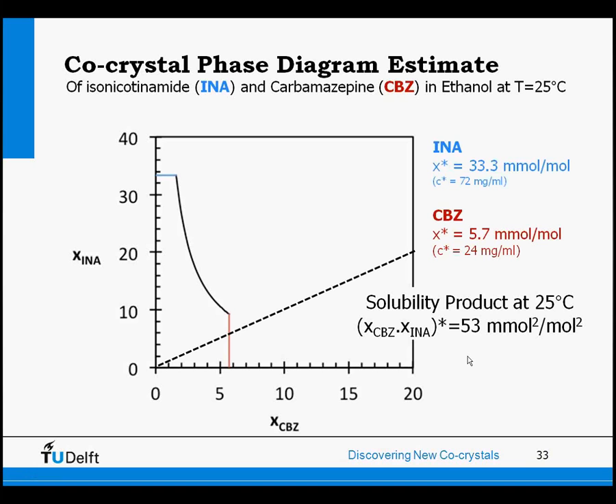And this line is governed by the solubility product of 53. And you see that the stoichiometric line does not really go through the co-crystal region. So if you would crystallize isonicotinamide and carbamazepine from 1 to 1 stoichiometric solutions, you would not obtain co-crystals from those solutions. You need solutions that contain about 6 times more isonicotinamide than carbamazepine.